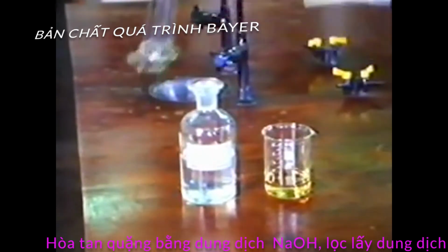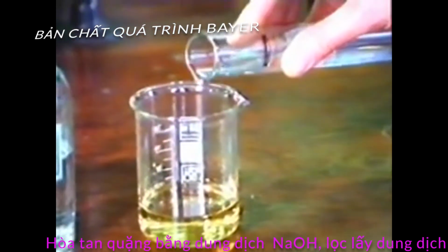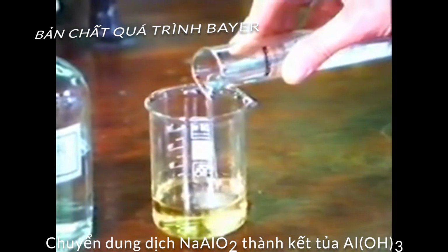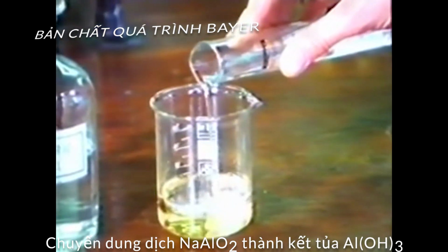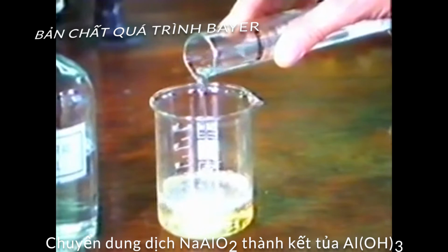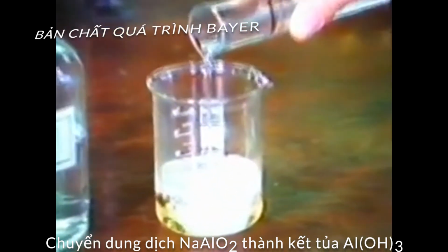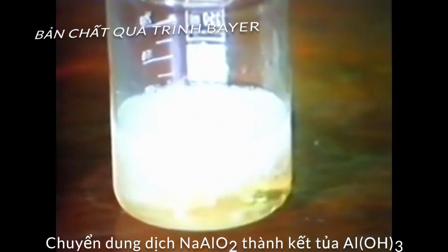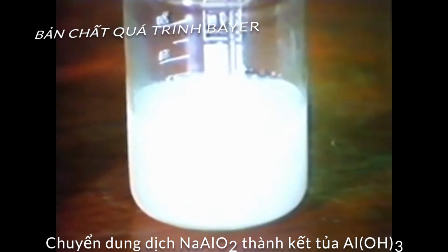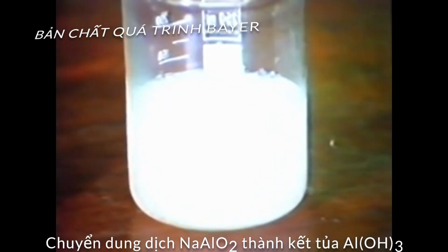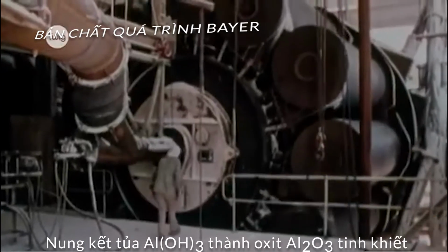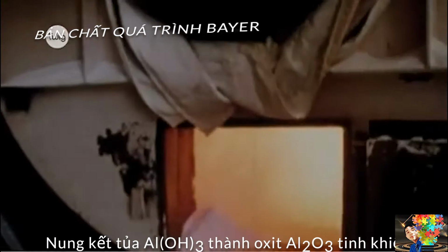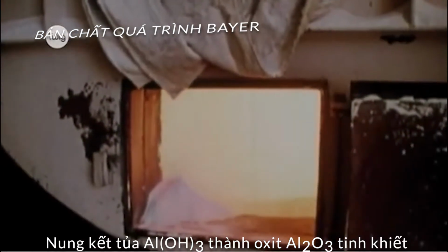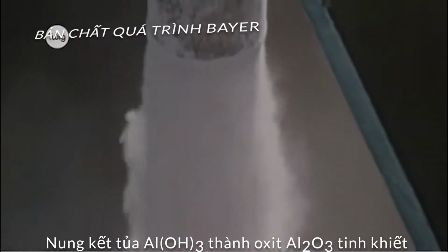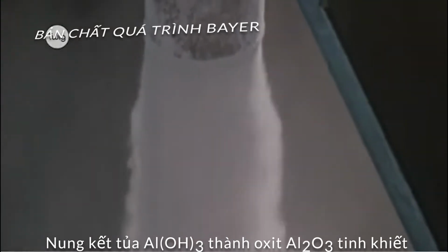If we now acidify the filtrate, the sodium aluminate is decomposed and pure aluminium hydroxide is precipitated. This pure white aluminium hydroxide can be filtered off and heated to produce pure alumina, aluminium oxide. The mixture is heated to 1,200 degrees Celsius, causing all of the water to evaporate, leaving a dry white powder, alumina.